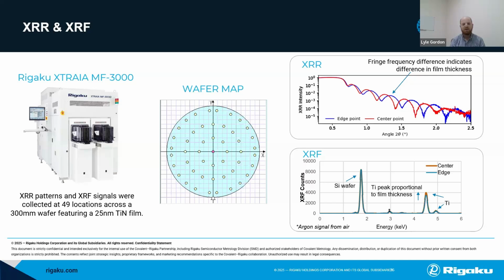And we can take all the points and model them and do the similar thing with the XRF, where you look at the intensity. However, here it's a bit harder to see. If you look closely, the peak labeled titanium is a little bit higher in the center than the edge because it's thicker in the center. And then we see the big peak from the silicon wafer characteristic X-rays.